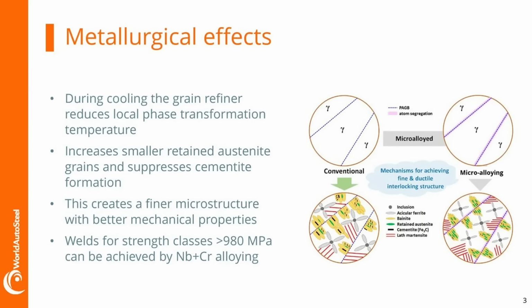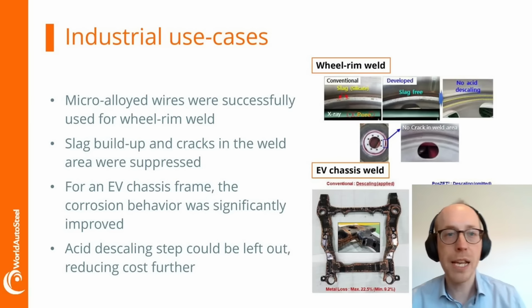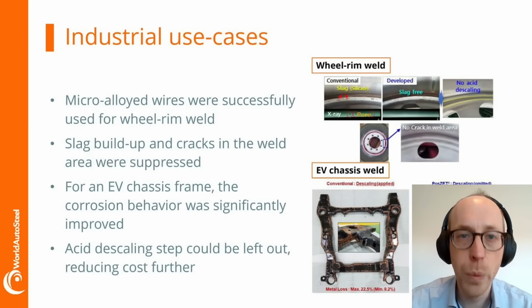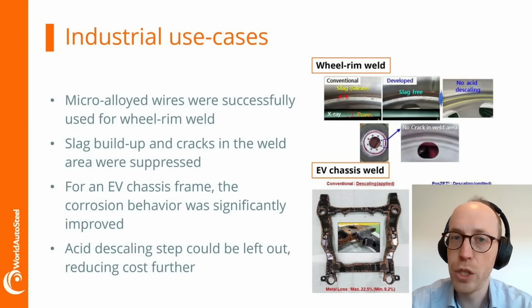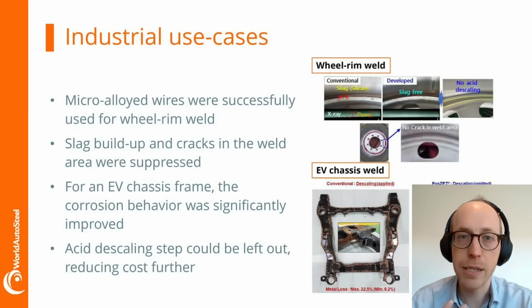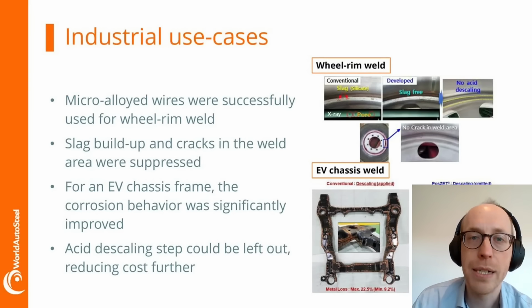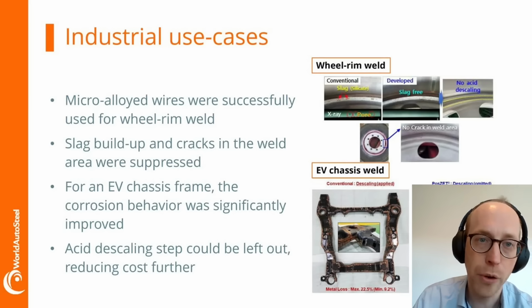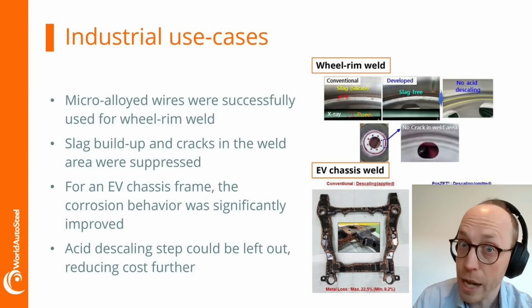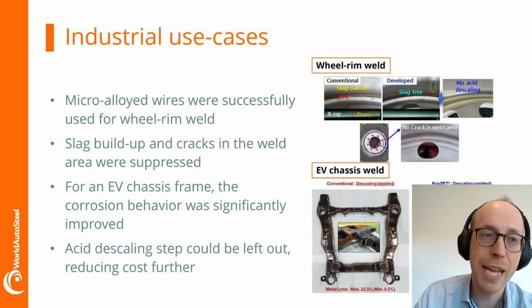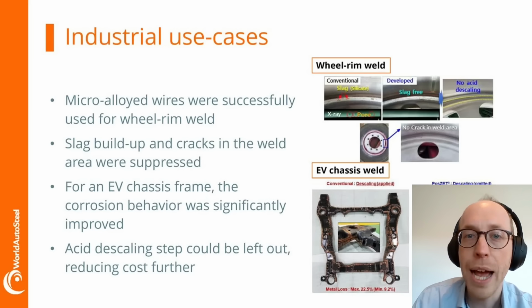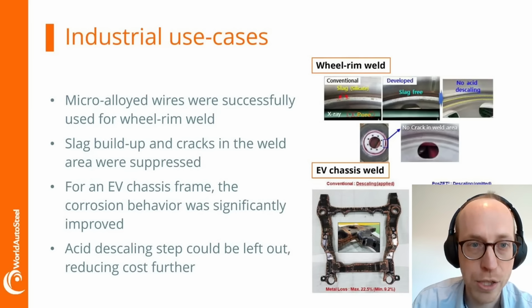If you want to weld very high strength classes, such as 980 megapascals or more, some alloying concept, for instance, is using niobium and chromium microalloying. If we look at some industrial use cases, we have the wheel rim weld on the top, where in a conventional weld we get slag and pores in an X-ray test. And in the new microalloyed welding wire, we don't get any slag, so we can save on a descaling, on a cleaning process, and we also don't get any porosity or any cracks around the welded zone.